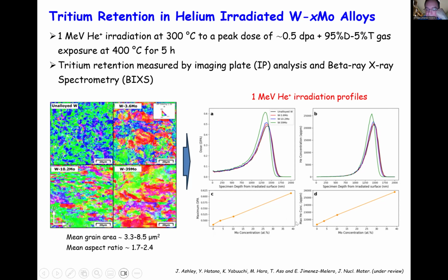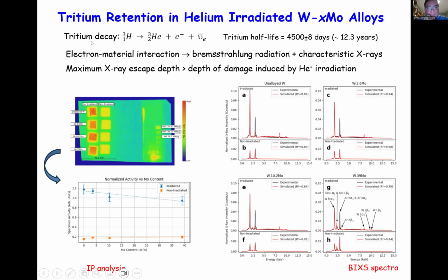and look at how it evolves or changes with the amount of molybdenum. What is more impressive, I think, well, first of all, the tritium decays into helium, electrons and what's called an antineutrino. That tritium has a half-life of around 12 years. So we don't want to lose tritium, and we don't want tritium in any reactor component that later is going to cause radioactive waste. Now, those electrons have a given energy or energy distribution that interact with the material and cause what's called Bremsstrahlung radiation and characteristic X-rays.